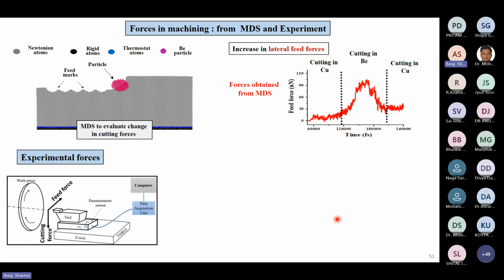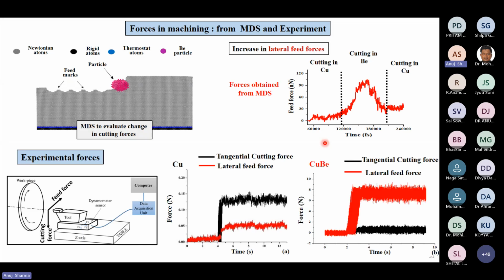And I also checked in the experiments. That also showed that initially the cutting forces were higher, but as the tool wear took place for copper beryllium, the lateral feed forces were high. So in the case of copper, the cutting forces were higher, and for copper beryllium, the lateral feed forces were higher, which were causing the tool to level that surface. So that's why the random lay pattern was observed.